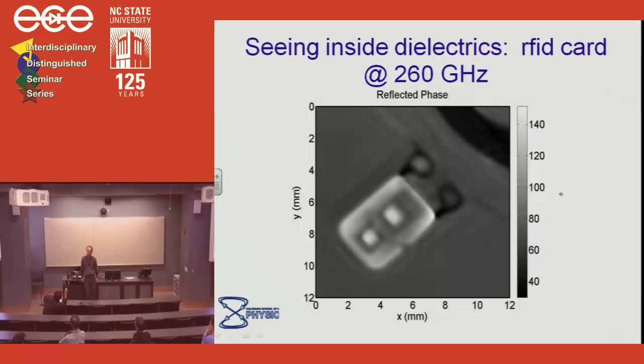And can you imagine then basically using something like a flash laser? I guess I would have to ask, what is your ultimate objective? There's lots of different kinds of images. For example, we use speckle interferometry to image the strain in samples, and we can image the entire sample in one shot. We illuminate the sample with speckle, do some signal processing, and out pops the entire strain field. But if you wanted to measure the dielectric properties locally, you have to confine the photons to that local area so that they're not averaging over nearby areas. And that's what takes you a while. So it really just depends on what measurement you want to do.